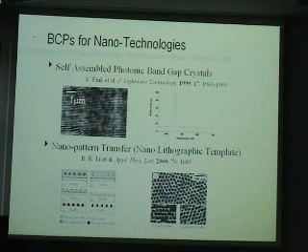Actually, in case changing the dimension of this dielectric stack, we can control the reflection light range. In this particular case, we can reflect about 450 nanometer range. We achieve almost 100% reflectivity using this self-assembled structure.